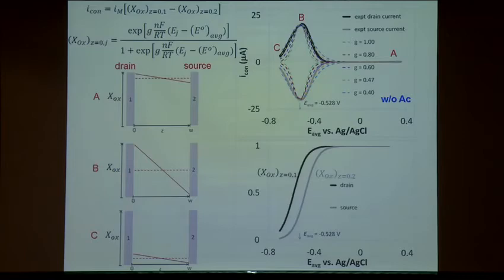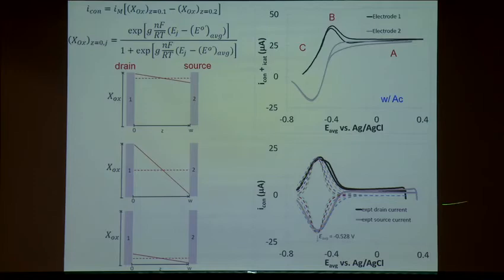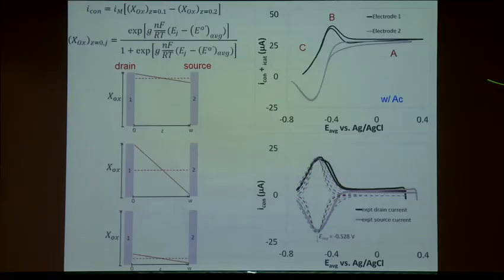And then finally, we can actually do it in the presence of acetate. And these curves get a little bit complicated. So this is electrons flowing into the biofilm from the one electrode, and this is flowing out from the other electrode. But both electrodes are simultaneously acting like anodes and oxidizing acetate. We can subtract out the acetate contribution. I guess you can read about it in the paper. And what's left is a current going from one electrode to the other, and it's qualitatively the same whether there's acetate present or not. We can drive electrons through the biofilm from one to the other.